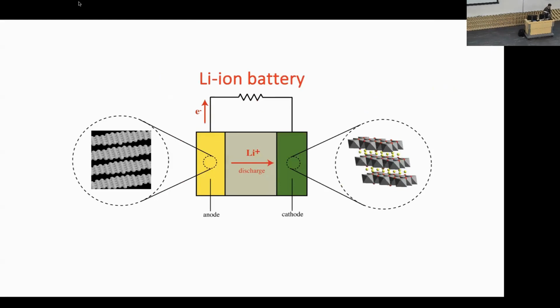Let me just get the schematic out of the way in case you don't know how a battery works. It has three components. Two electrodes, an anode and a cathode. They are electronically conducting materials separated by an electrolyte, which is electronically insulating, but allows cations of a particular type. In lithium batteries, it would be lithium plus ions that diffuse through them. The anode typically is something like graphite, and the cathode is typically a transition metal oxide, if we're talking about a lithium-ion battery. And the lithium ions like to insert between these layers.